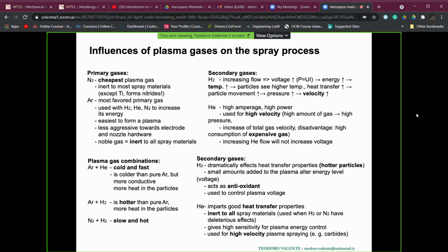For what concerns secondary gases, hydrogen is very important, as already said before, because it has a very important effect on heat transfer properties. I mean, we have higher energy, so we can heat the particles more, and it can act, that's an important point, also as an antioxidant, reducing, also when spraying in air, the amount of oxides which could be formed, since it's a reducing element.